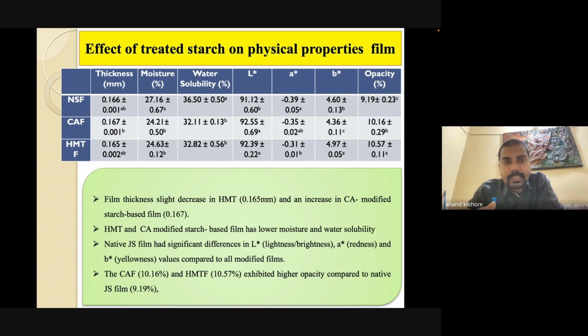It may be because thickness basically depends on the formulations and the volume of your samples. In this case, the formulation is the same for all samples, and the volume we have taken is the same. So maybe that is the reason there is no significant change in thickness. But moisture and water solubility are again lower if we modify the starch. Similarly, it affects the color parameters also. The lightness value increases in the case of modification. The opacity also increases in the case of modification. So it is a better sign; it means the modification technique affects the quality of the film.